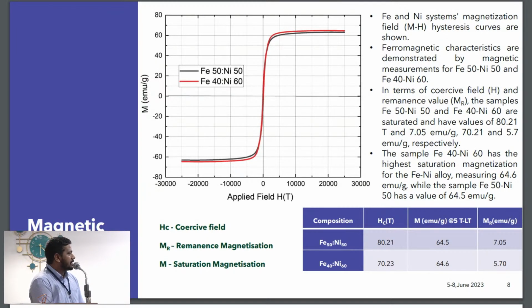For the magnetic property, VSM, the field dependent magnetic property of both the samples was taken, and from that we got coercive field for the 50-50 is higher, that is 80.21, and for 40-60 it is 70.23. The remnant magnetism for the 50-50 sample is 7.05, and for 40-60 it is 5.70. The magnetic saturation for the 50-50 sample is slightly decreased, that is 64.5, and for iron nickel 40-60 it is 64.6.